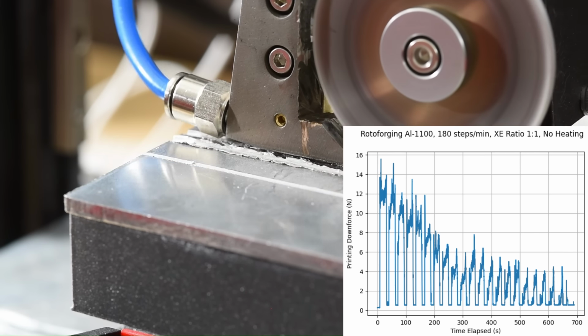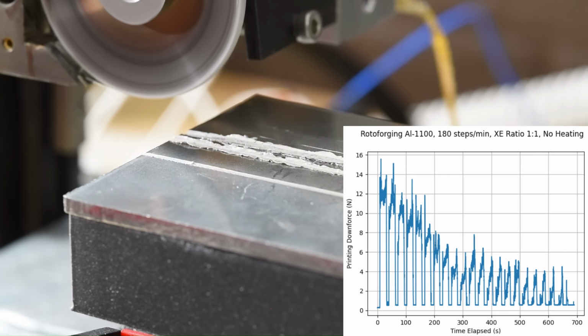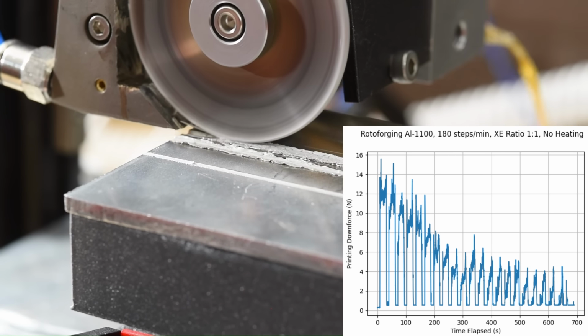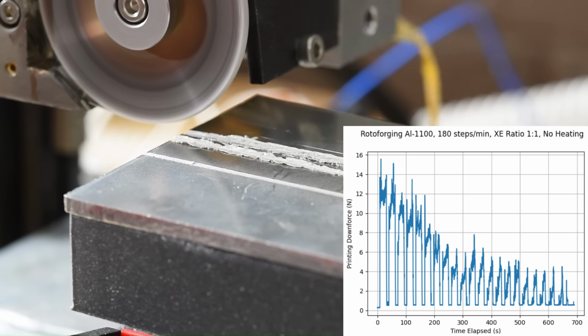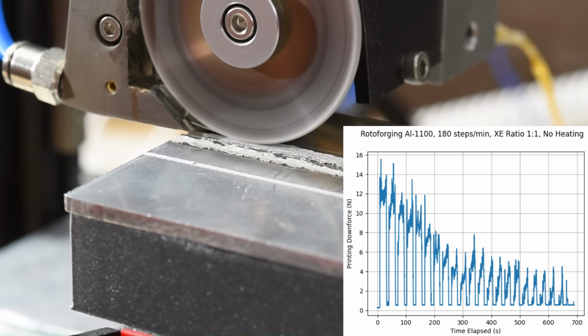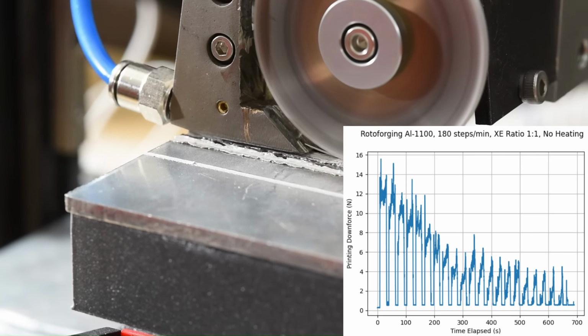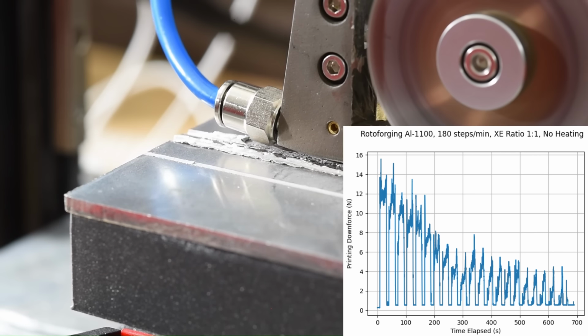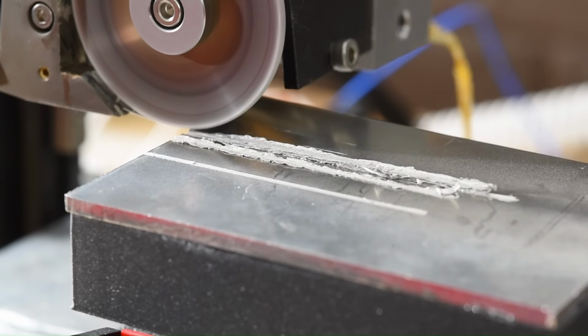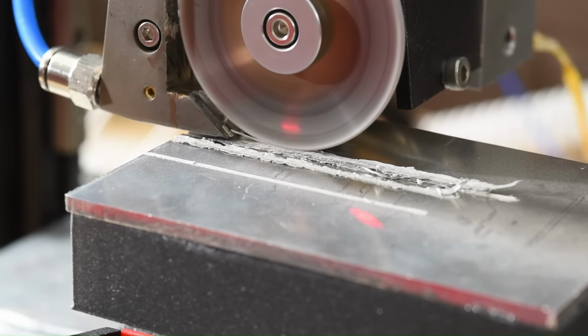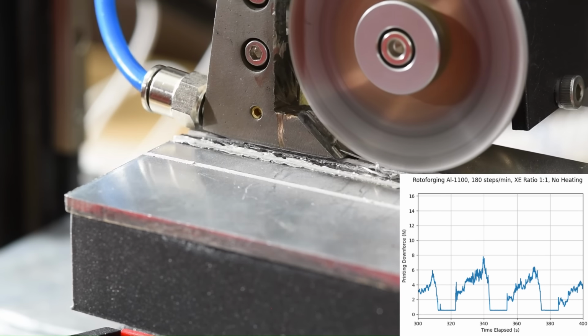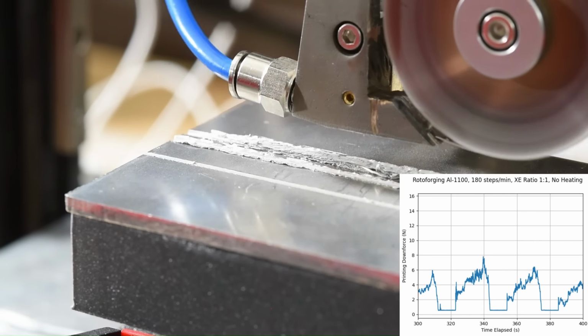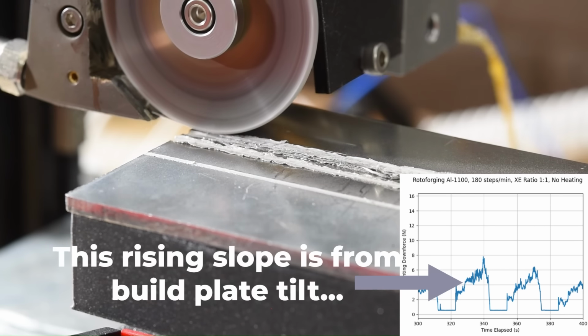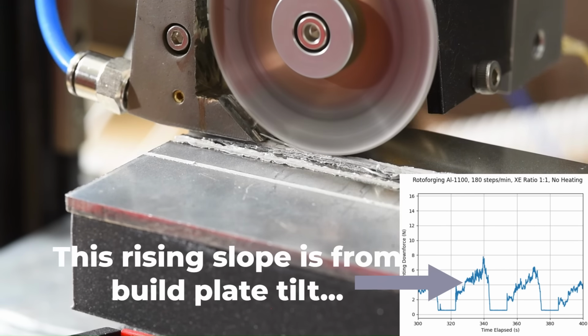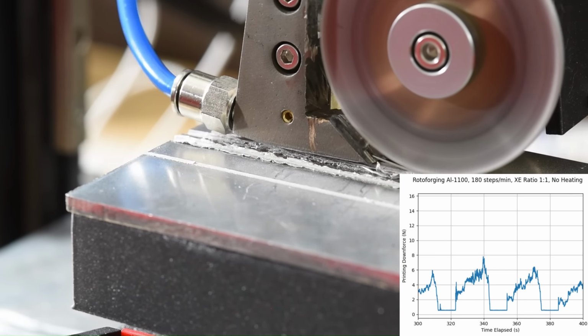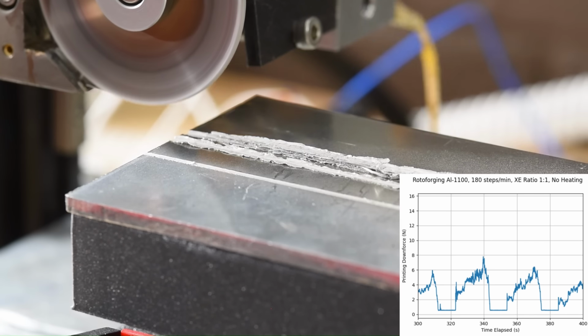Of course, our process forces tend to decline towards the end of this run because the build plate is tilted and the engagement depth changes throughout the run, so there's a sharp rise in the slope from the start to the end of each deposition pass, and the wheel is getting steadily farther and farther away from the surface as we're printing. So at some point, it fails to start and the deposition stops. But as you can see, the steady-state deposition forces are quite mild, even under less than ideal circumstances with relatively poor control.